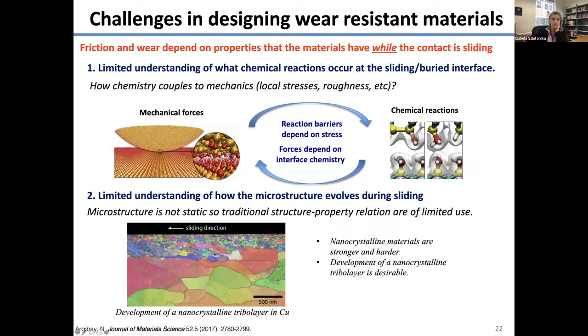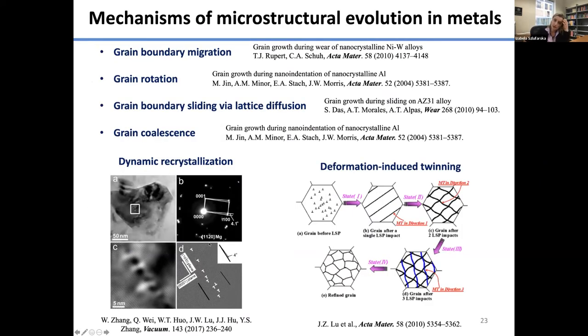However, there's a limited understanding of how this microstructural evolution takes place, which materials will show it, and how to control this microstructure evolution. So we were interested in that, and there are multiple mechanisms that can drive microstructural evolution during the deformation of metals. Some of the most common mechanisms for metals are shown here. So we have grain boundary migration, grain rotation, grain coalescence. They typically drive the grain growth.